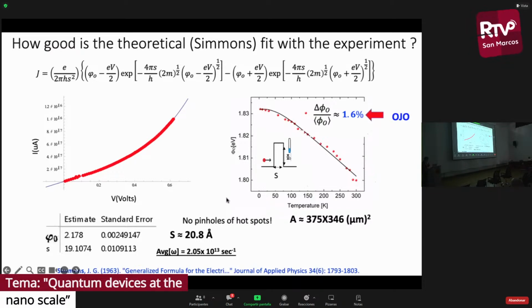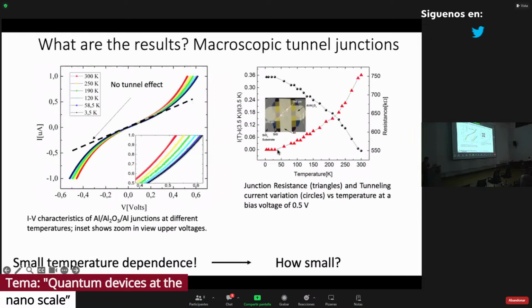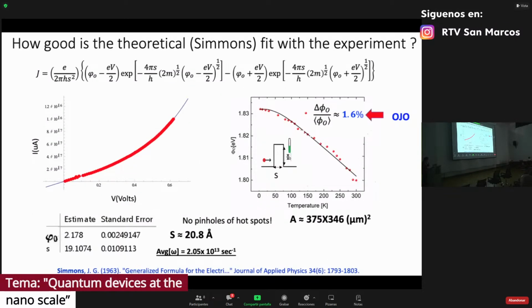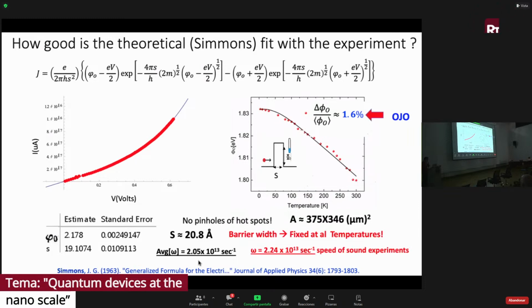And that will help us to explain what's going to happen later. So when you do that, you can see that the barrier height is increasing when you lower the temperature. One thing I have to remind you quickly: in our case, the thickness of the barrier is the thickness of the oxide layer, about 20 angstroms, 2 nanometers. And the barrier height is 1.8 electron volts, or 2 electron volts, depends. You can also get the phonon frequency from these measurements. You can get a lot of information from there.